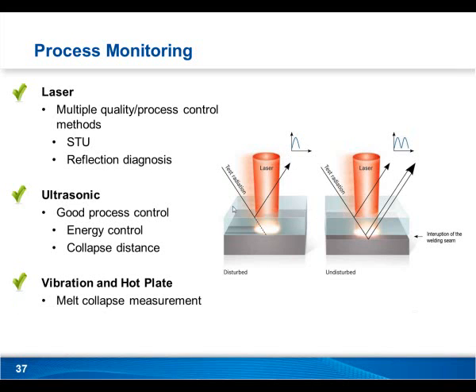Essentially what you're looking at here is a reflection diagnosis system, and what's happening is the test radiation is being applied. So this isn't the same as the laser. It's being applied at a specific angle, and then as you can see here, when there's no gap, you're only going to get one angle of reflection. And so the system will monitor this reflection, and that's going to feed back and say that this is going to be a good clean joint here because there's no gap. However, if there's a gap, which remember we want to avoid because we need that conduction to occur to get a nice clean weld, then there's going to be two angles here. And so the system will monitor that, send it feedback, and at this point the laser could actually in real time slow itself down and heat this up a little bit more, hopefully bridge that gap.